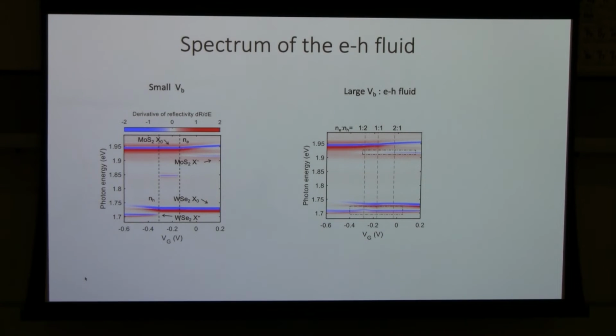So now you can inject the electron and hole at the same time. So again, at 1:1 ratio, you can see the exciton and the trion, exciton and trion. So basically, both regions are doped. But if you look carefully, there is also some additional spectral change that happens around this region, where the density of electron to hole is 1 to 2. And if we zoom it out, we can see this spectral feature is actually pretty obvious.